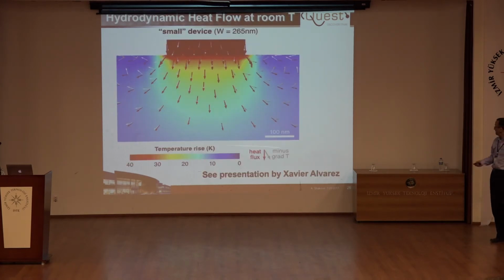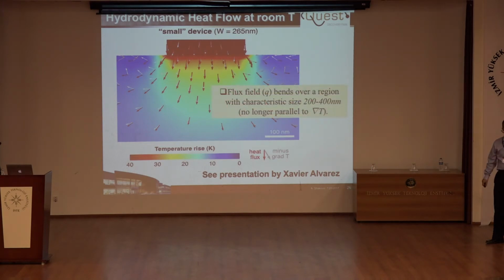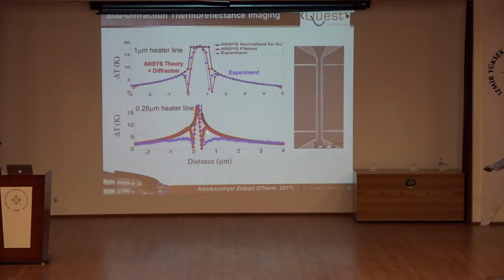It took us some time, but Xavier's work explains what happens: when the devices are smaller than 1/2 a micron or so, you have a heat source on top of a substrate, you have vectors of a heat flux and vectors of a temperature gradient that can be not parallel. This is one of the indications of a hydrodynamic flow of heat, because if the heat is purely diffusive, the two should always be parallel. With this type of modeling, Xavier and his group were able to exactly explain the full temperature distribution which was here. And I guess Xavier showed it on Monday, so I won't go over those.